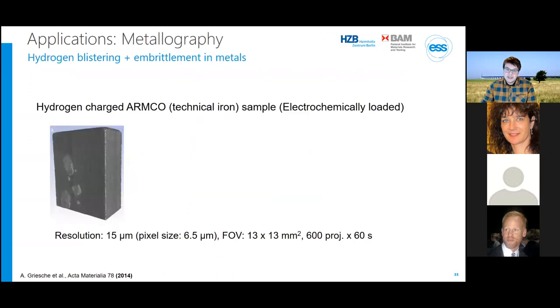Now I like to switch gears a little bit. We are now dealing with a metallic sample, and neutrons are often used to complement the more standard metallographic characterization techniques. And hydrogen embrittlement is a field that is a tremendous problem that hinders us as a society to develop and deploy stronger metallic alloys. Prominent failures related to hydrogen embrittlement include those of bridges and oil platforms, for example. In the example that I'm showing here, colleagues from the BAM in Germany have excessively charged an iron sample with hydrogen up to a point where already blisters were formed.